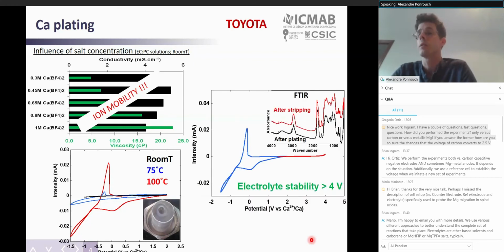This was done in carbonate-based solvents, a mixture of ethylene carbonate and propylene carbonate, using calcium BF4 as the salt. This was done on purpose to assess the feasibility of the plating and stripping in the presence of a stable passivation layer, which was confirmed to be formed by means of infrared spectroscopy, and was stable upon cycling.